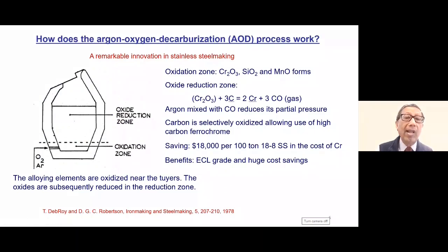You see, what I am showing to my left is a typical steel making converter. And people inject oxygen and argon through the lower end through what we call tuyeres. And as soon as oxygen gets in contact with the iron, carbon, chromium, nickel melt, they form oxides of those elements. They are lighter than the metallic melt, and at that time, chromium oxide gets reduced by the carbon in the melt to form chromium.